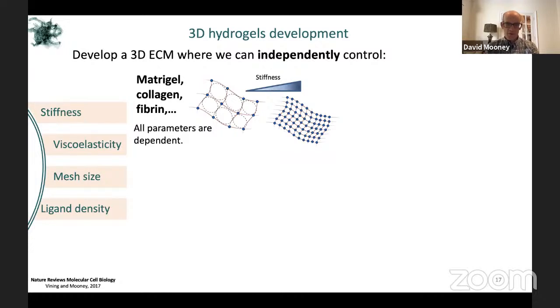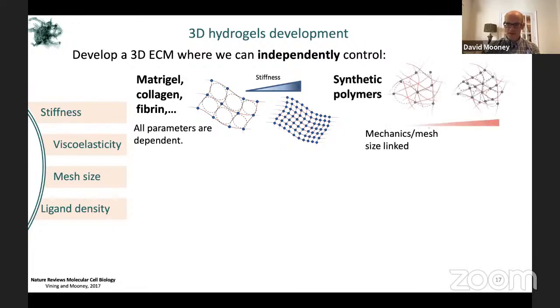So the reason we don't use materials like Matrigel or collagen or fibrin as they are traditionally used in the biomaterials field is that while one can readily make stiffer or less stiff gels out of these materials, this is typically done just by adding more and more material. And this makes the gels more stiff, but also increases the number of adhesion sites. It actually decreases the spacing between the gels, or the mesh size, which can lead to changes in diffusional transport of things like macromolecules. So all the variables end up getting basically dependent in this setting.